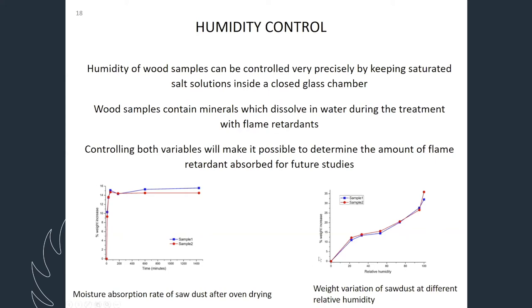In another test, we dried the wood samples, but now we made a humidity chamber. And it's quite easy to construct. We took a glass chamber, a 5 liter chamber, which we can cover with another glass. And inside the chamber, we kept a saturated salt solution of different salts like sodium nitrate, magnesium nitrate or magnesium chloride. And if we cover the glass chamber, the humidity remains quite constant. And it is a very efficient method for controlling humidity.